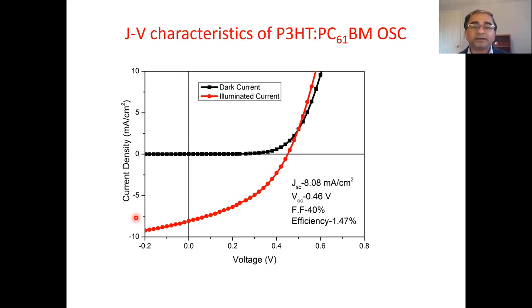So these are the IV characteristics of an actual device which I have fabricated. You can see that this point gives you the value of JSC, this point gives you the value of VOC, and this area, if you calculate it, will give you the value of fill factor. And when you put all these values together, we get the efficiency of the device. So this is my first device, with very low efficiency of course, but this is my first device with P3HT:PCBM, which is the most popularly used material in organic solar cells.